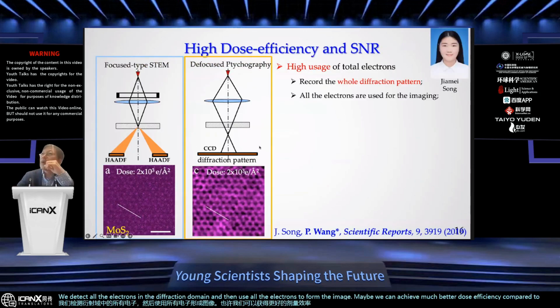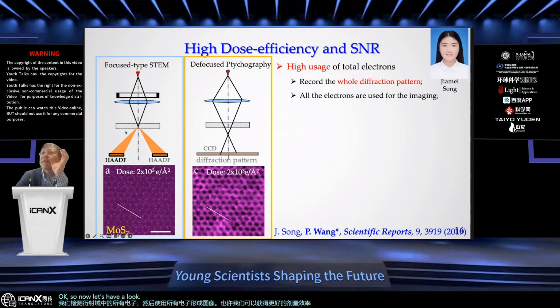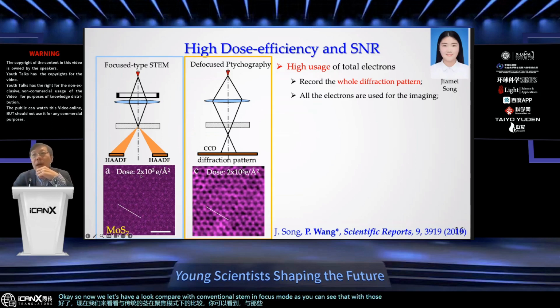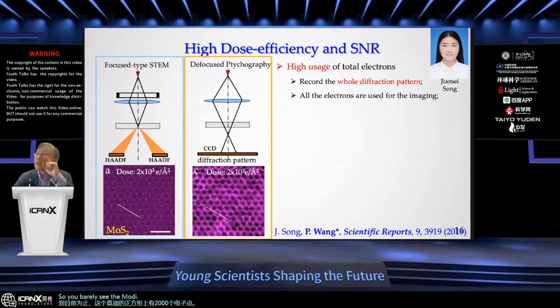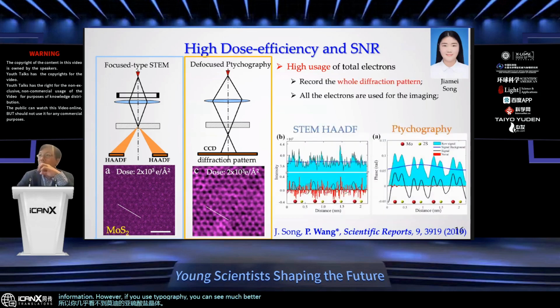Okay, so now let's compare with conventional STEM in focus mode. As you can see, with an electron dose of 2000 electrons per angstrom squared on this molybdenum disulfide sample, you barely see the molybdenum disulfide crystal information. However, if you use ptychography, you can see the atomic columns much better. If you draw a line profile across the atomic column in the STEM mode, as you can see,